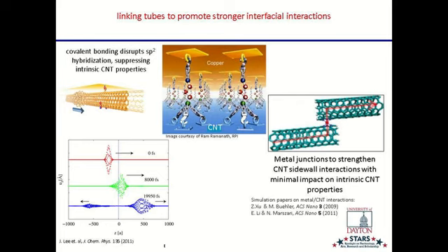Remember, I talked about the difference between carbon nanotubes and diamonds. It's sp3 versus sp2 bonding. I'm converting the sp2 bonds in this carbon nanotube to sp3 bonds, and the conduction is poor. So I'm improving the interface but ruining the nanotube itself. This is not the way to go, and there are other practical problems. It's not thermally stable, with lots of these linker molecules, or a whole host of reasons to not use them.